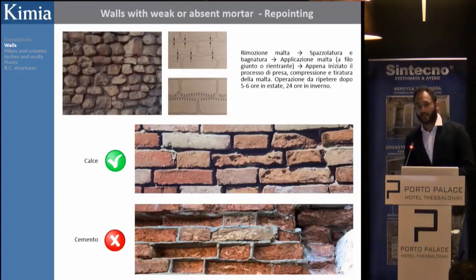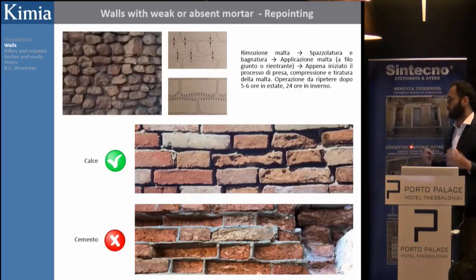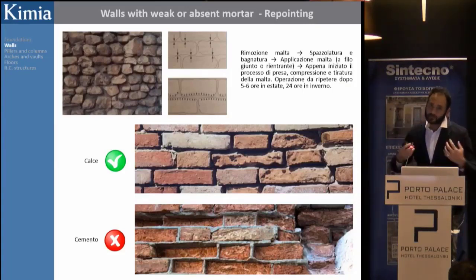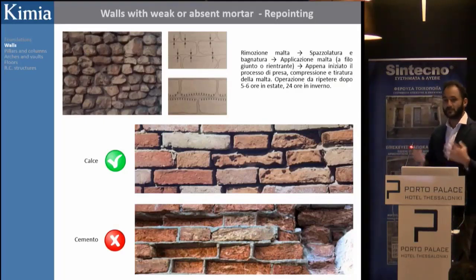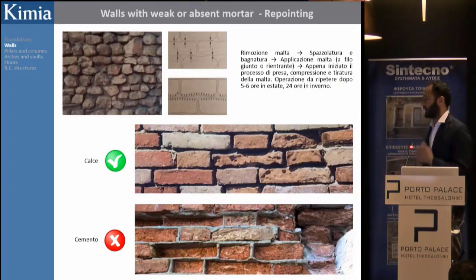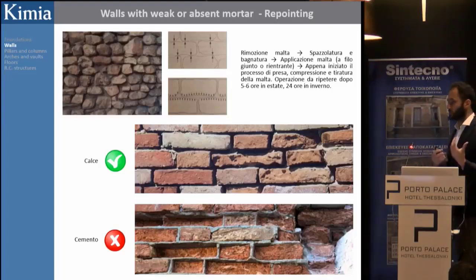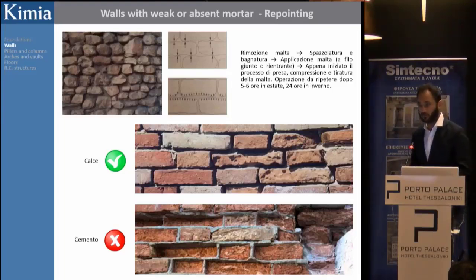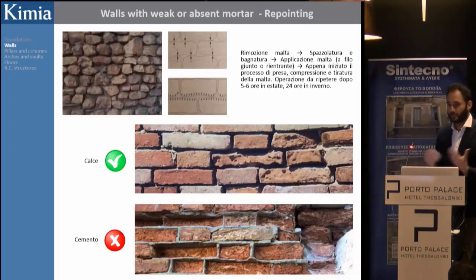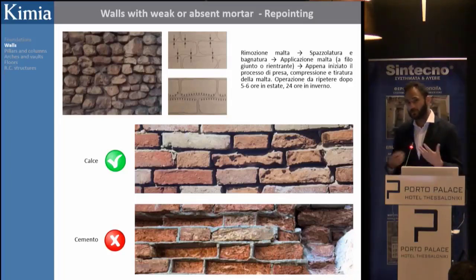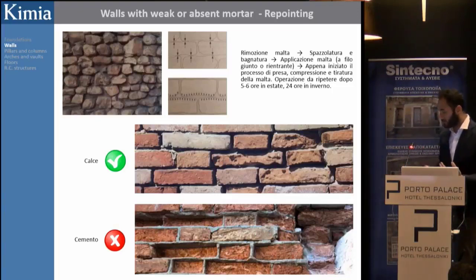But another problem again arises. Okay, let's say that it is very important that we deep repoint the walls so that the overall behavior of the walls will be the best possible. What material am I using? Again, in the past, sometimes the idea was the stronger, the better. So I will use a cement-based mortar, which is maybe the strongest product. And so the idea was that I'm increasing a lot the original resistance of the walls. But some problems arose, like you see here.